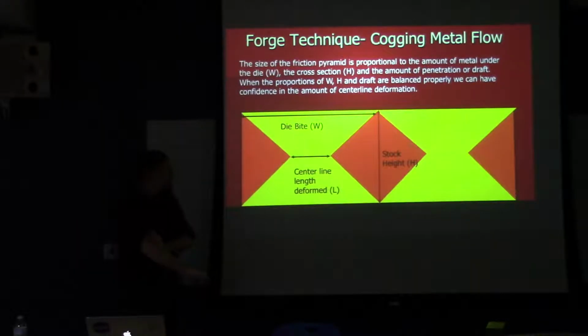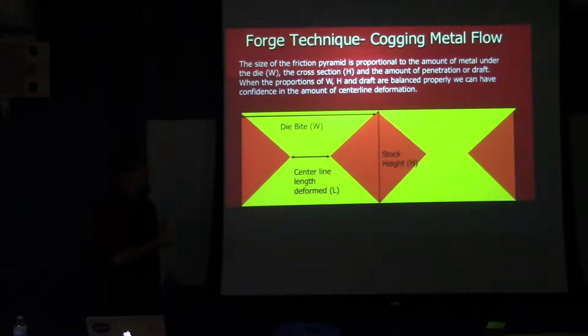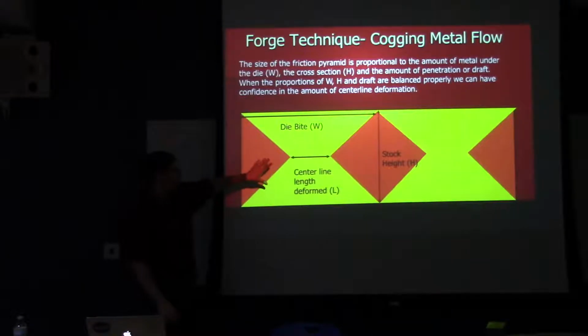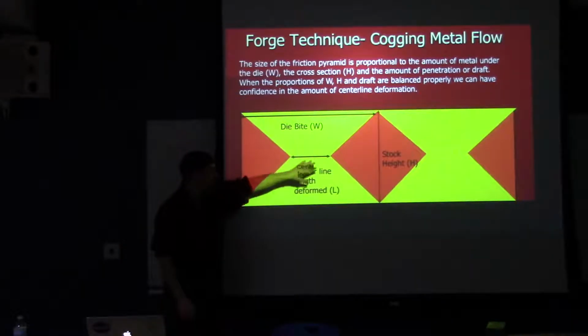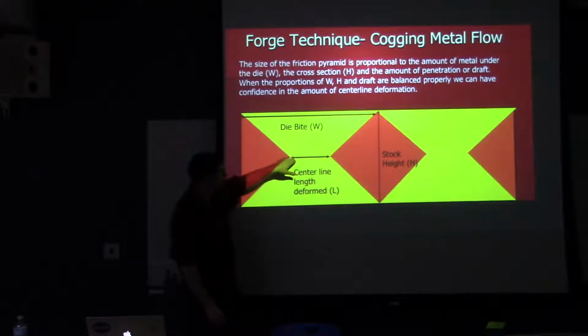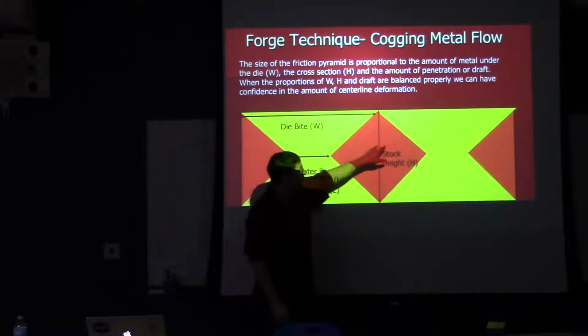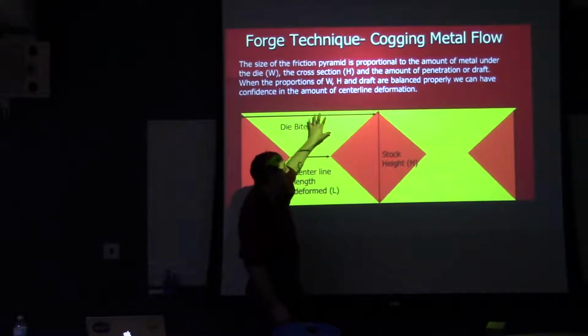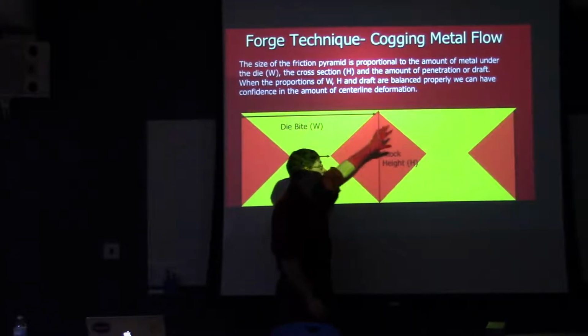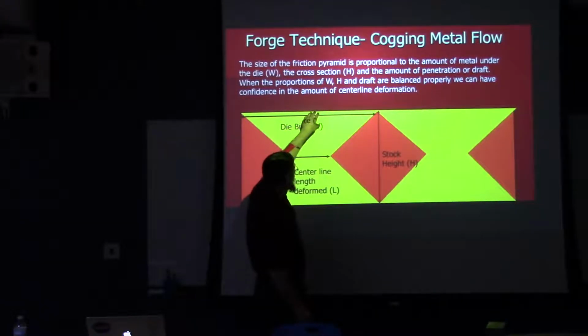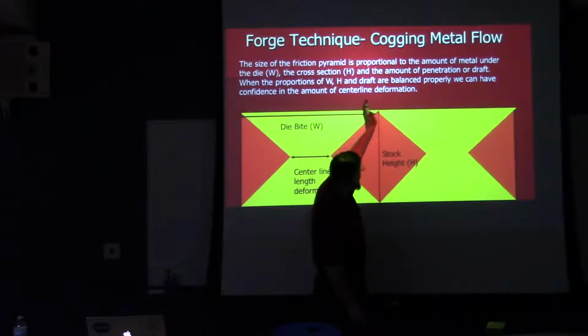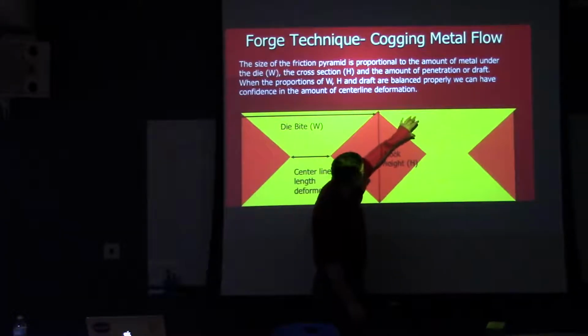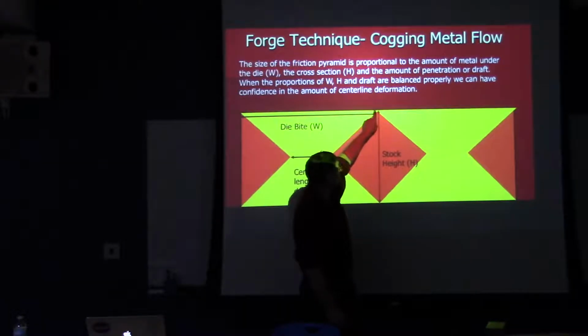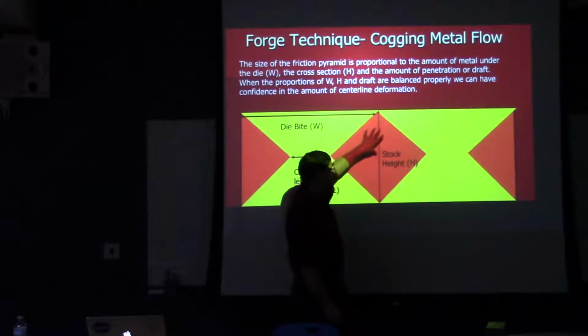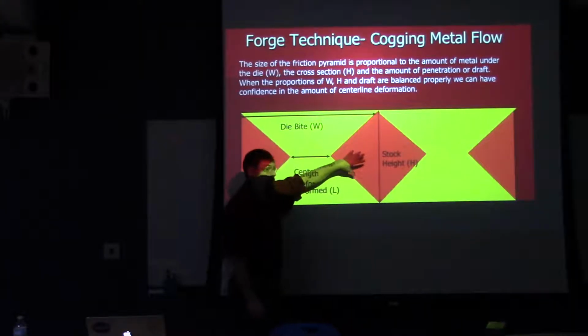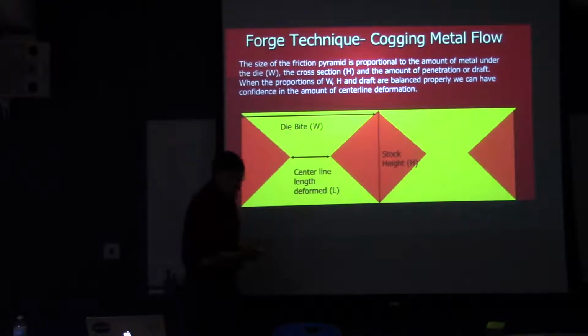So, this is, I think, about where we stopped last week. I've represented our two friction pyramids that have collided along the center, and here's the gap in between these two adjacent die bites, right? So the press has come down and squeezed here, and then we've moved over just enough, and again, these two die bites on the surface are right next to one another. There's no gap, even though at the center there is a gap. That's because of this effect of the friction pyramid.